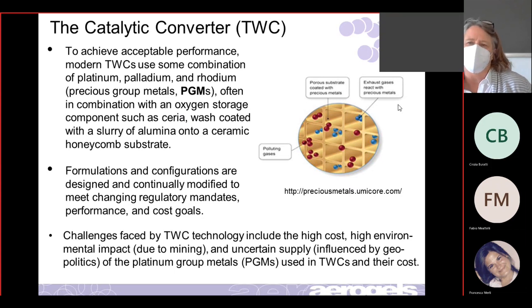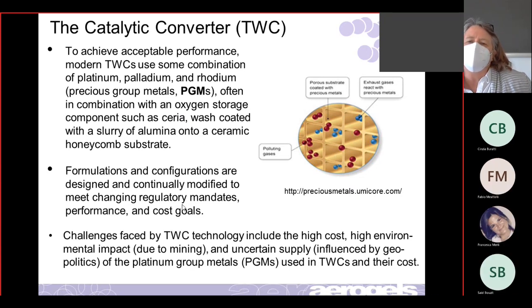And so there are many, many formulations and configurations. And by that, I mean how much platinum, how much palladium, and how much rhodium do you use in your setup. And sometimes they're designed in two parts. One will have more of one, and the other more. One might have more palladium, the other more rhodium. So it's very challenging for the automotive industry to keep up with designing these.